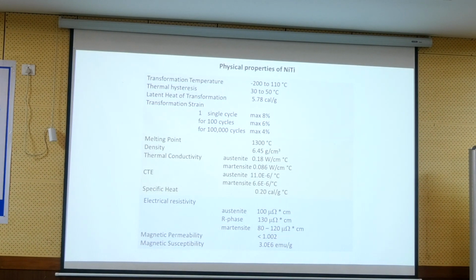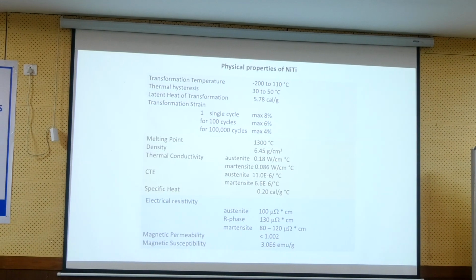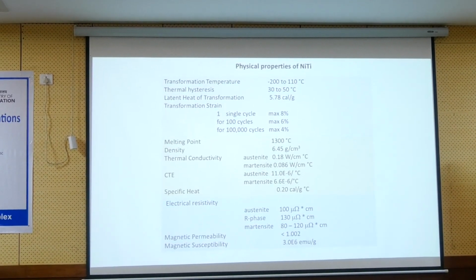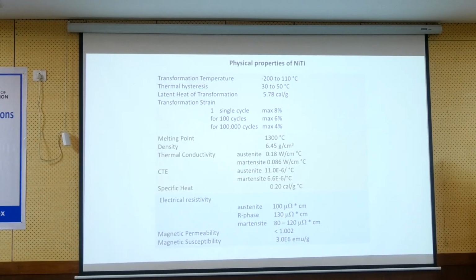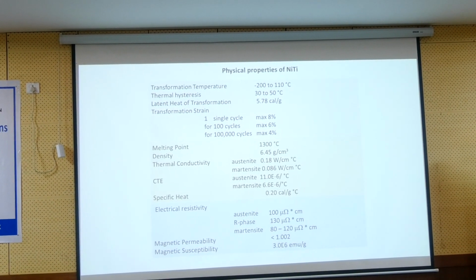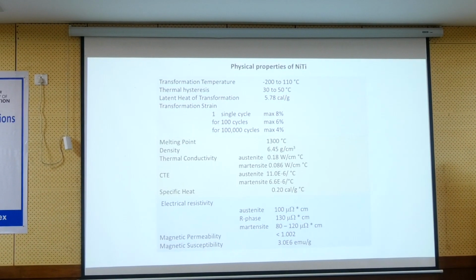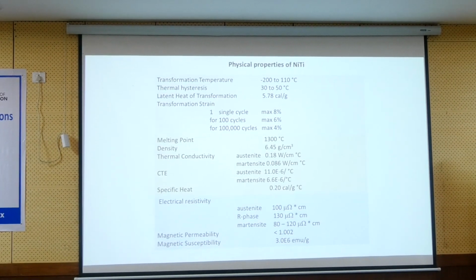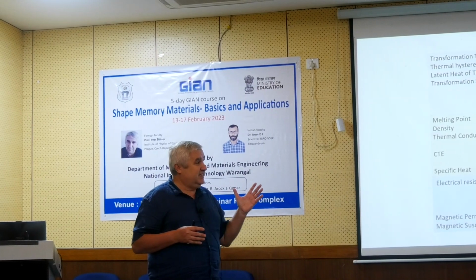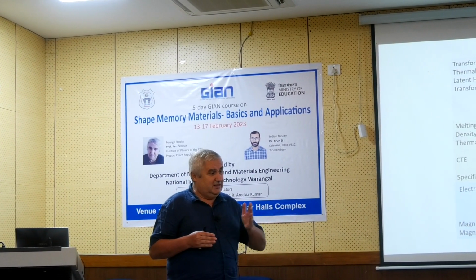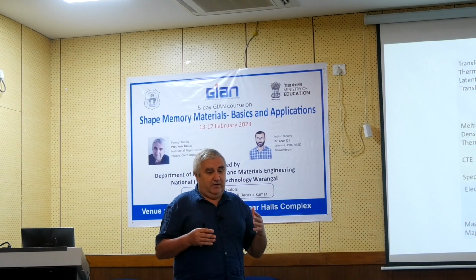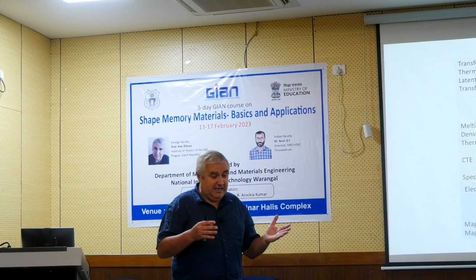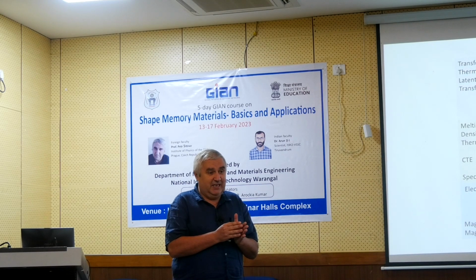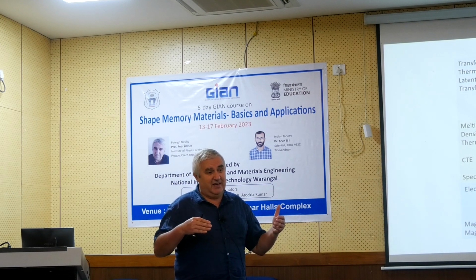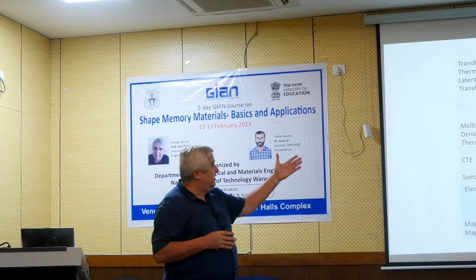The thermal hysteresis is put here as 30 to 50 degrees. Of course, I also took this information from physical tables. This is very funny because if you have a NiTinol wire and do superelastic cycling, you can decrease the hysteresis to 10 degrees, which means that the inherent hysteresis of the material is probably much lower than 30 degrees. It can go down, but it is connected to the habit plane motion we discussed yesterday. So when NiTinol transforms from austenite to martensite, it has to solve this problem of strain compatibility, and this needs some excess undercooling and overheating, and because of that you get hysteresis like 30 to 50.